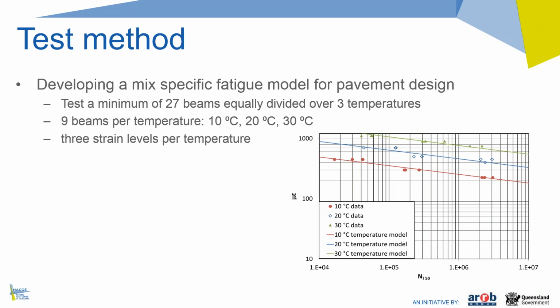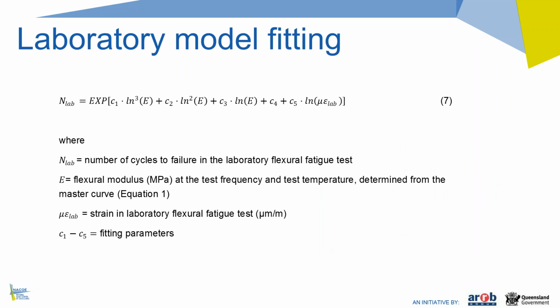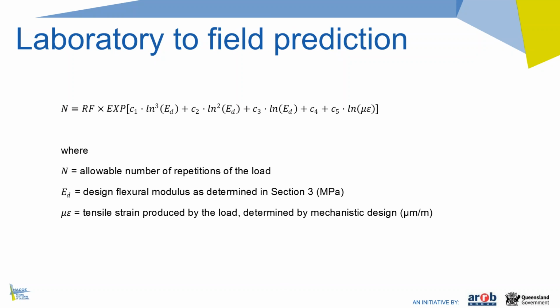Okay, then for tests to develop mix-specific fatigue models in accordance with the tech note, we need to test 27 beams equally divided over 3 temperatures, 9 beams per temperature, so that's at 10, 20, and 30 degrees C, and that will give us enough statistical confidence to fit our model to the data. The model that we'll be fitting looks like this. It's slightly different from the Shell model. The Shell model was basically a 3-parameter model. This is a 5-parameter model. And the reason for using this model instead of the Shell type model is that it's more sensitive to temperature changes. And you'll basically be fitting this model to your fatigue data and solving it for the 5 different regression parameters, C1 to C5, to come up with a mix-specific laboratory model.